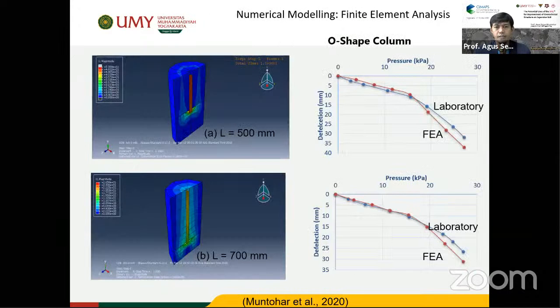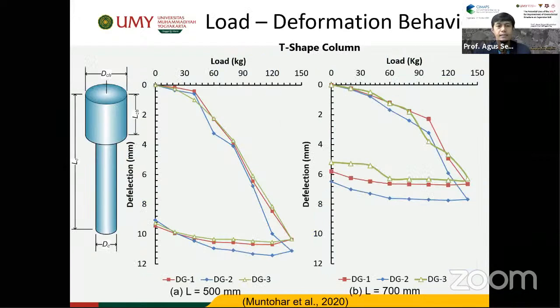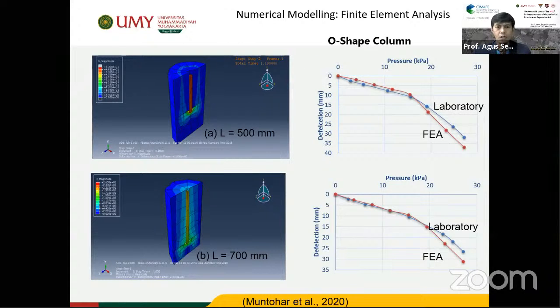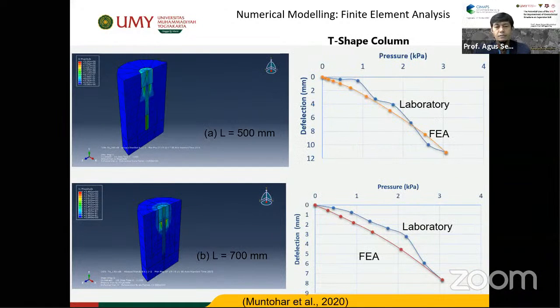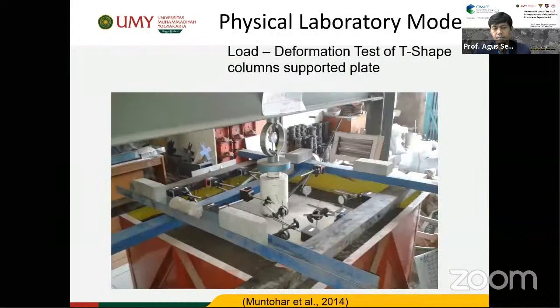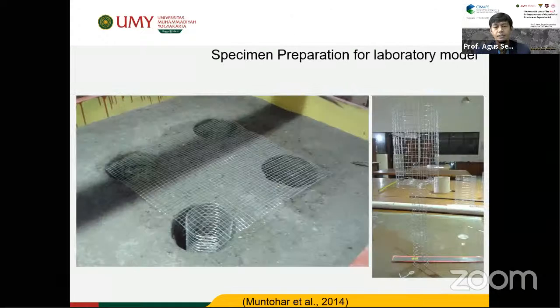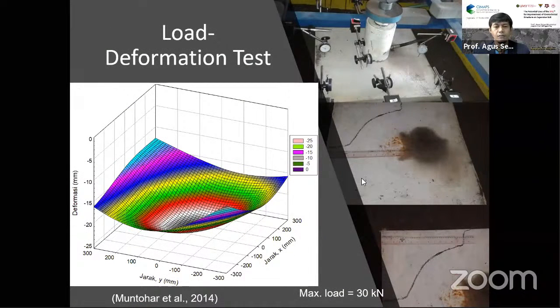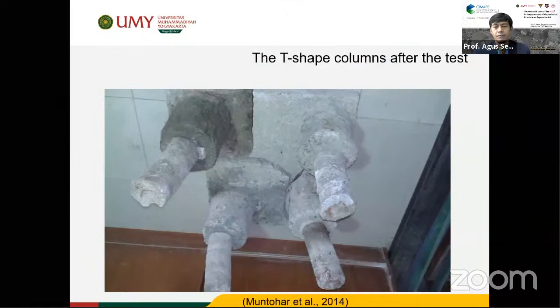This is our calculation, and also this is from the laboratory tests, and then we did some verification with the numerical modeling. Okay, this is our model. This means there is the laboratory and the finite element analysis. And then from this laboratory model, we tried to do some other models in our laboratory. And this is the result from our load and deformation analysis. The maximum load for our model is about 30 kilonewton, around 3 tons. This is the typical T-shaped column after the test.